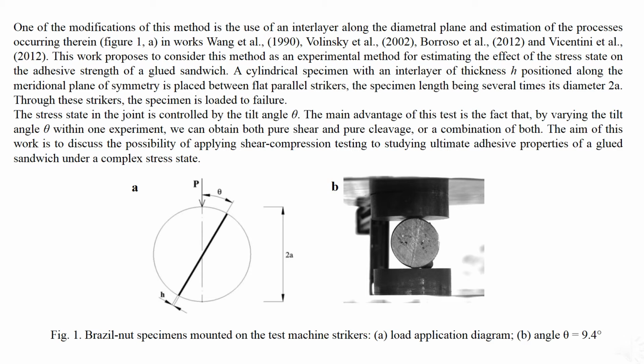The main advantage of this test is the fact that by varying the tilt angle theta within one experiment, we can obtain both pure shear and pure cleavage, or a combination of both. The aim of this work is to discuss the possibility of applying shear-compression testing to studying ultimate adhesive properties of a glue sandwich under a complex stress state.